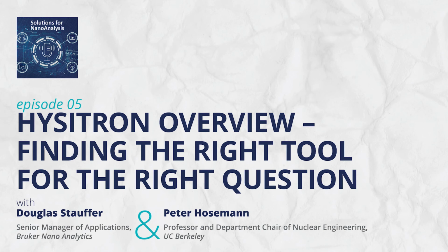Because 200 displacements per atom at 0 Kelvin means that your atoms stay displaced. Yes, yeah. They don't relax back into their favorable condition. Exactly. Yeah. 200 dpa at 0.9 times the melting point of the material means they're all going to jump back to lattice sites and it's not going to do anything, right? Yeah. Or the extreme example would be 200 dpa in a liquid means nothing because there's no lattice site.